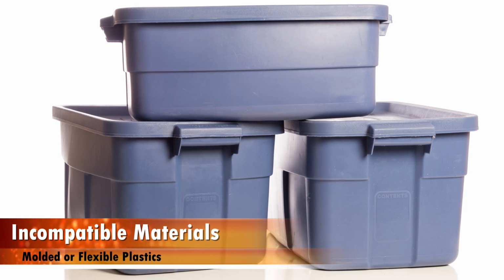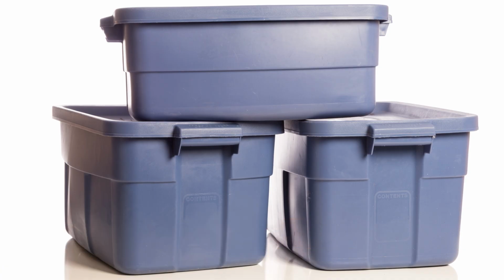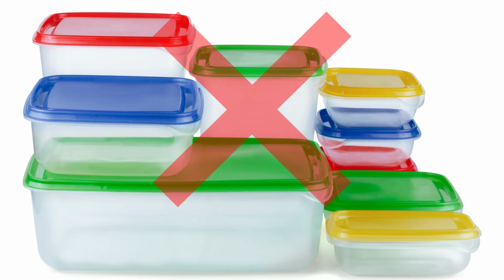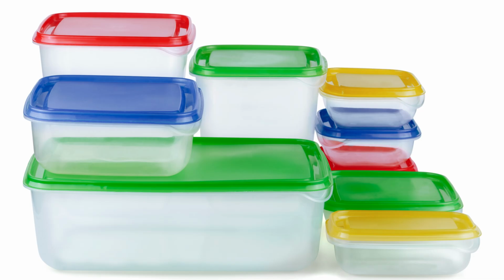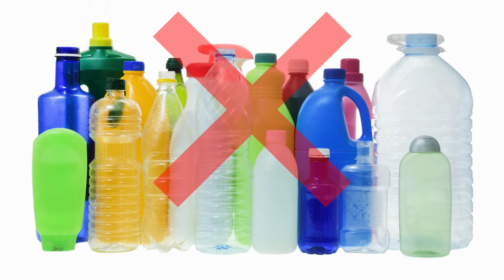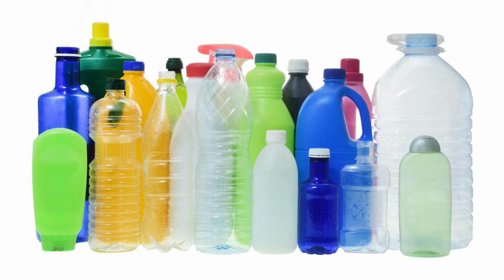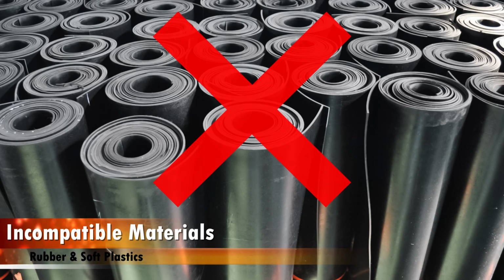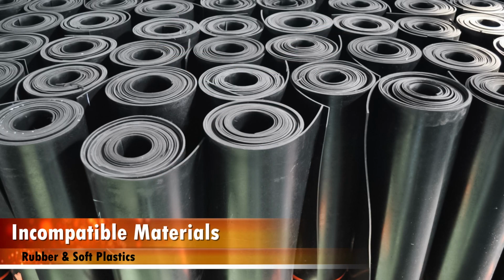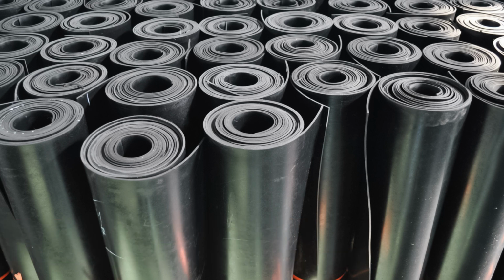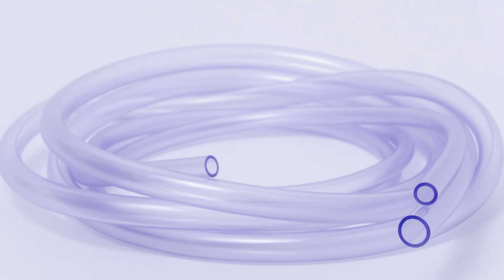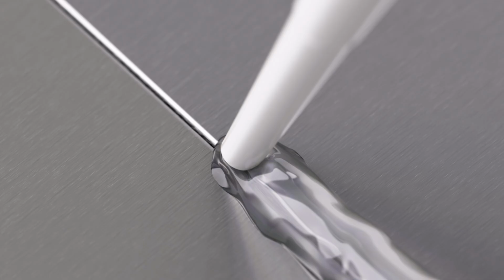Concrete should never be applied over a molded, flexible plastic structure without additional support. This includes polyethylene, polypropylene, polystyrene, and nylon. These materials alone provide little support, and adhesion failure or cracking is likely. Epoxy clay, however, will stick to molded plastics, but be sure to sand and clean the surface first. Never apply concrete or epoxy clay over any rubber-based materials. This includes neoprene, latex, urethane, and silicone rubbers. Concrete and epoxy clay will not adhere to rubber of any kind, especially silicone. Silicone is unsuitable for the structural demands required for concrete applications, leading to potential failures in both integrity and safety. Some silicone also contains chemicals that will cause cure inhibition in concrete.